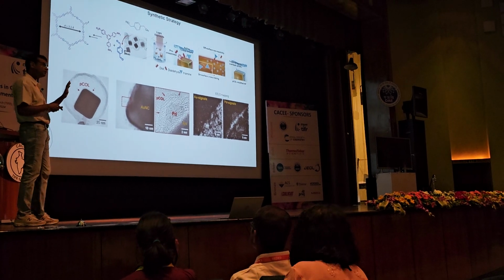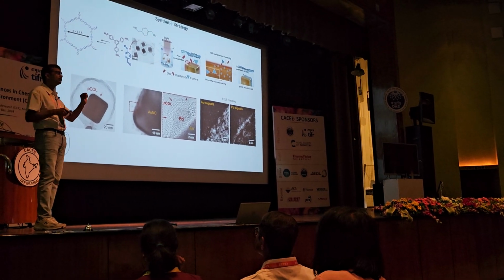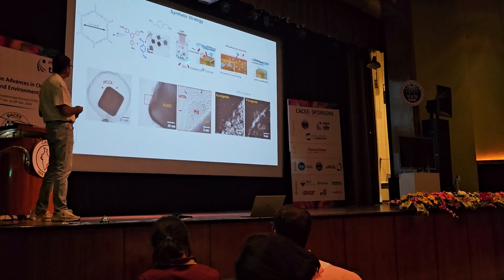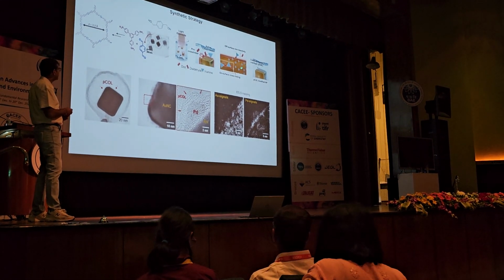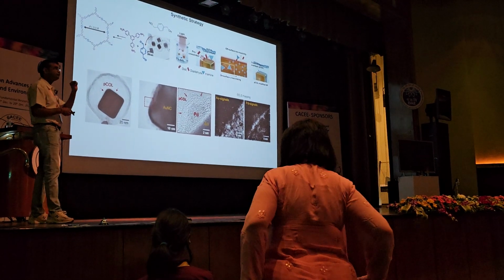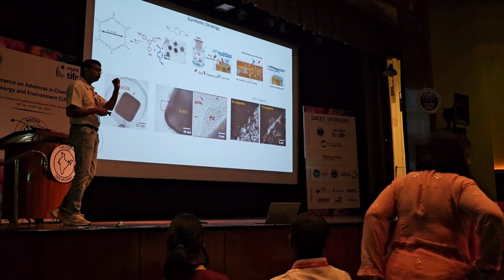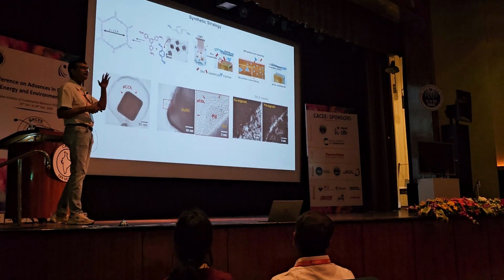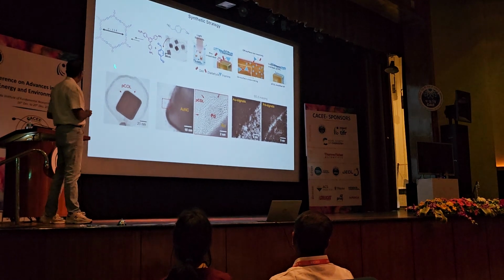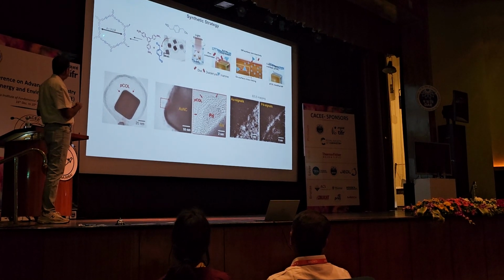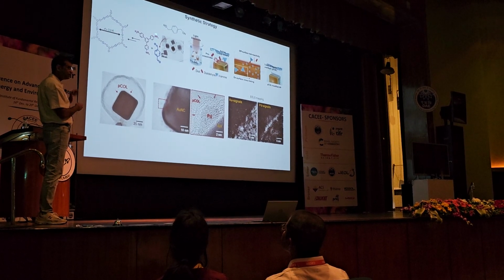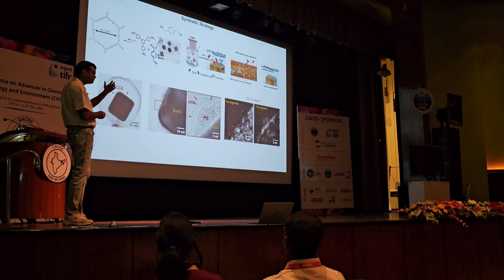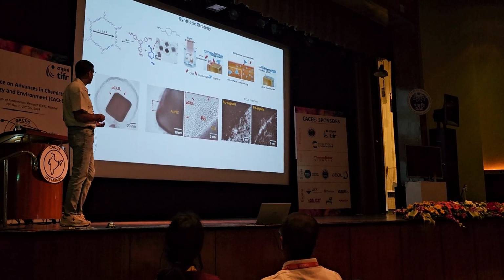But for COF synthesis, usually you cannot control the thickness or size of those materials very well. Here, due to this surface-limited chemistry, we could control the thickness within 2-3 nanometers. That ensured that this thin layer will not restrict the molecular entry. And the pore size is sub-nanometer, 3 to 4 angstrom, which can easily accommodate any small molecule.